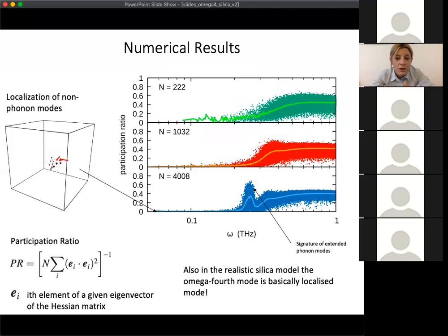We are happy because we observe this for the first time in a realistic silica potential. When we look at the bigger system size, we start to see the phonon contribution that starts to invade the low frequency regime, and if we increase the system size, this ω^4 behavior is smeared out. In order to get insight, we looked at the spatial information about the ω^4 modes. Previous research observed the ω^4 as localized modes.